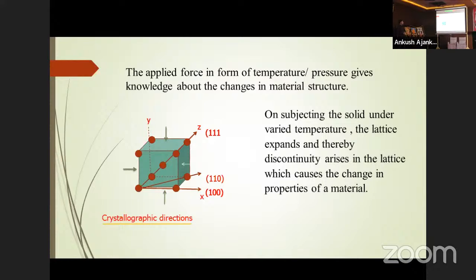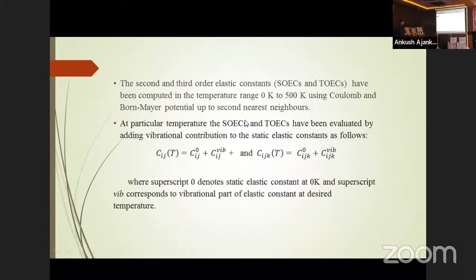When the temperature is varied on a specimen, the lattice expands and discontinuity arises in the lattice, which changes the properties of the material. The three crystallographic directions 100, 110, and 111 have been considered. The second order elastic constant and third order elastic constant have been evaluated at room temperature and with varying temperature. When we vary the temperature, the vibrational part of the elastic energy density contributes.